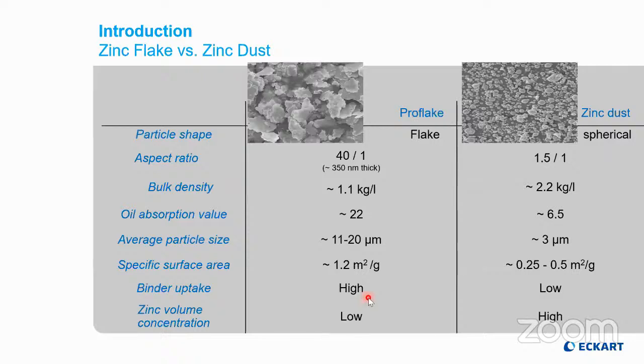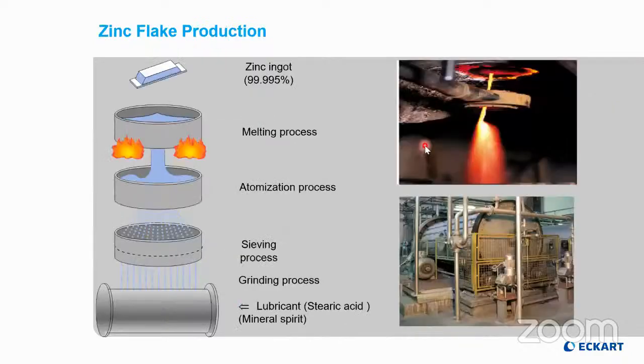This is very important to understand because, as I will explain, it later influences the formulation of zinc flakes in corrosion protective systems. We produce our zinc flakes in a two-step production process. Step number 1 is a melting process where zinc at roughly 420 degrees is molten, and the liquid zinc melt is pressed through a nozzle into the air. This process is called atomization, and the result is granular, more or less spherical particles. In the second step, we mill them, we grind them in a ball mill into the described flat zinc flake particles.